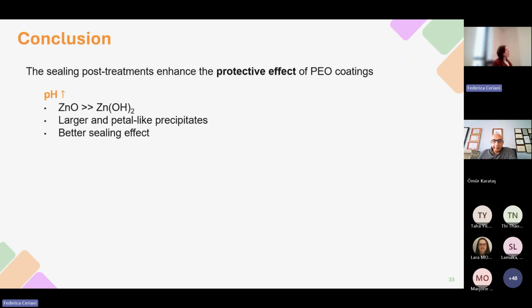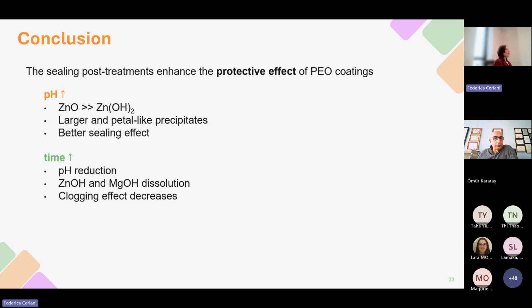the sealing bath, the formation of zinc oxide rather than zinc hydroxide precipitates is favored. These promote the formation of larger and petal-like precipitates that are able to better clog the porosity of the PEO coating, improving its corrosion-resistant effect. When longer sealing post-treatments are carried out, it is observed that the pH of the sealing bath is reduced, and this causes a partial dissolution of the already existent precipitates, causing a loss of the sealing effect.